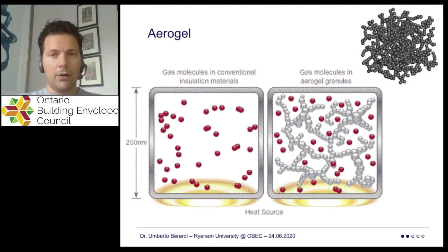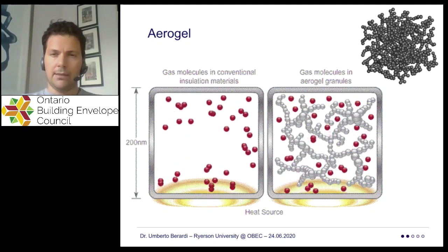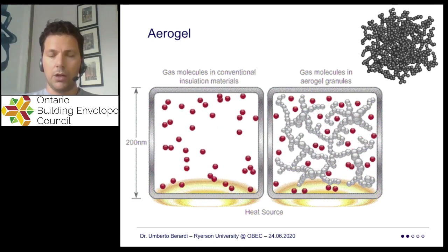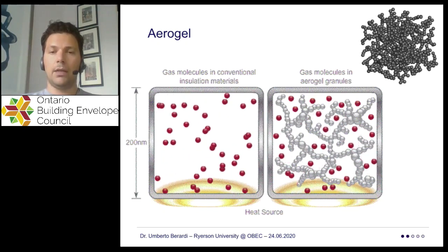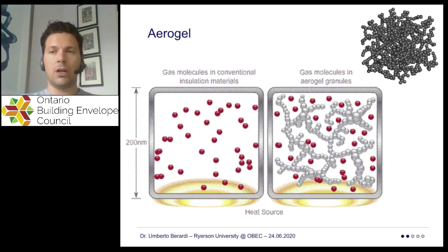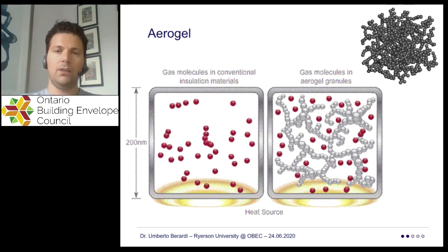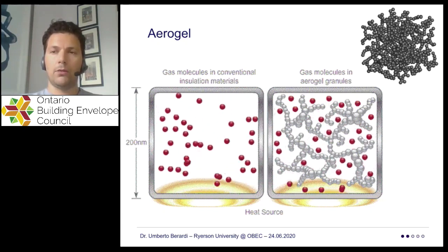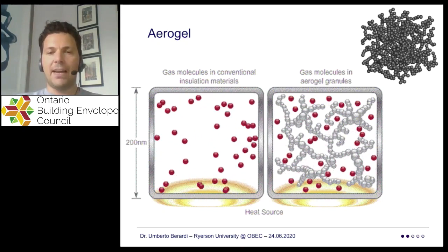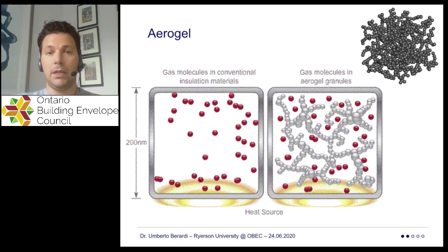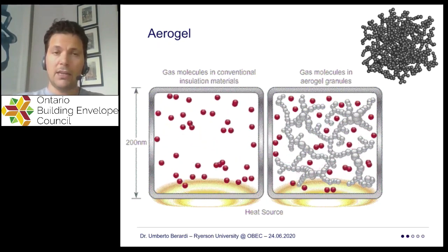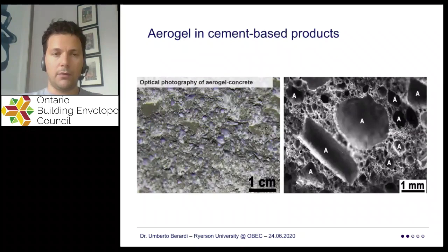And here is where the aerogel comes in. The aerogel is a material that has this very strange chain structure that prevents the red balls from moving a lot and limits them to this structure. By doing that, the convection within the porosity, within the cavities of these insulating materials, is limited. So the red balls can no longer move effectively and fast, and convection gets almost limited to zero in an aerogel.